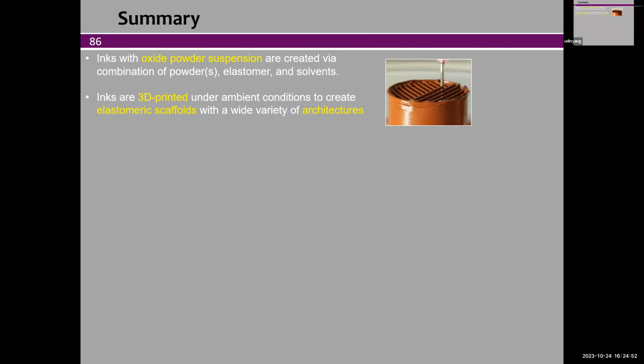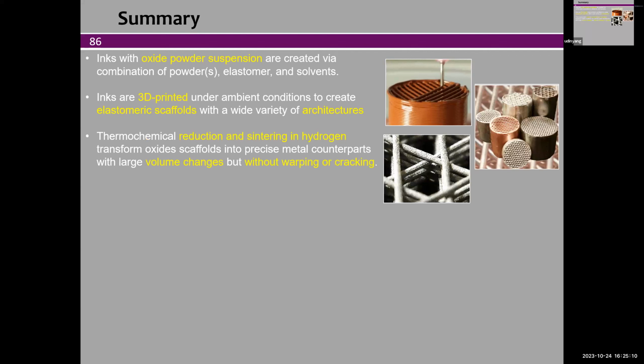So just a summary, we use inks with oxide powder suspensions by combining powders, elastomers, and solvents, 3D printed into complex architectures, from lattices to those more complex structures I showed you now. There is reduction and sintering happening, leading to large volume changes without warping or cracking.